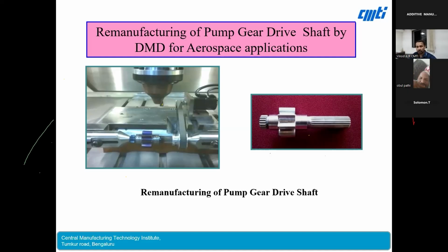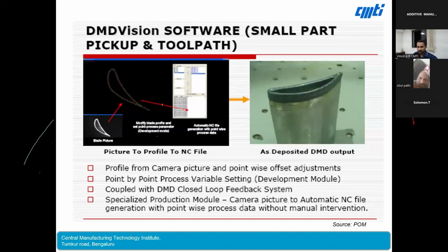By DMD we deposited on the shoulders, and then again it was machined by grinding. After that, when we tested at different conditions, there was no peeling off and it was satisfactorily performing in the test rig at HAL.